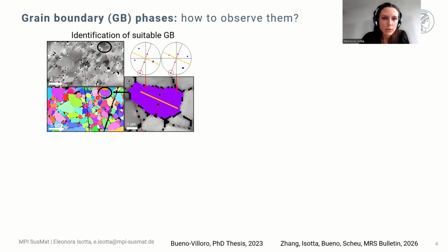When the ideal boundary is identified, we can proceed with cutting a lamella. There could be several reasons why we select a particular boundary. For example, one could be chosen because the two adjacent grains have a common zone axis, which leads to easier conditions for achieving atomic resolution imaging. Or we select a specific boundary because we have information from other measurements indicating that boundary is interesting, or we want to correlate the structure and chemistry with properties that were previously measured.